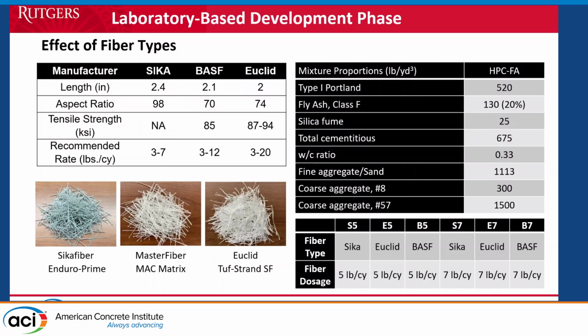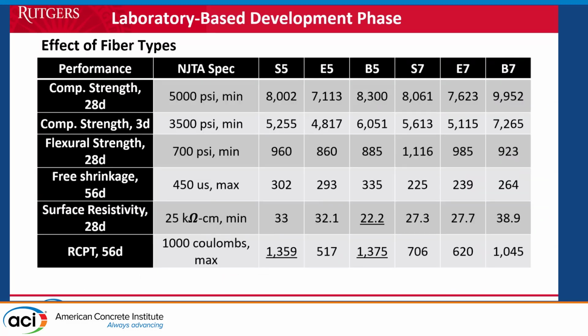This is a typical mix that had fly ash. To make it easier for the producer, they add 5 pounds to the mixing truck, the transit mixer. They batch it as if it's an HPC, then run the drum at a certain speed for about 2 minutes, and then keep it running at a lower speed when they're driving it to the site. This was the way we wanted to do it, because it was fast production based on the requirements of the producer. And you can see this is the general specification.